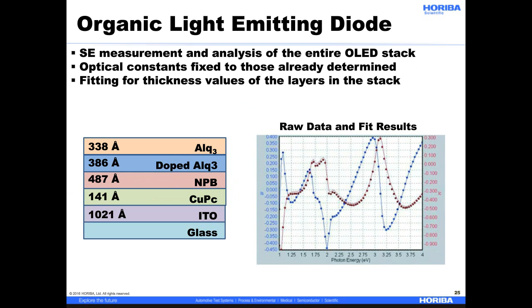Finally, you have the whole stack. This is the SE measurement and analysis of the entire OLED stack. The optical constants are all fixed to those that were already determined, and we're basically fitting for the thickness values of the layers in the stack. You'll see on the right some raw ellipsometry data and the fit results, and on the left you'll see the thicknesses for each layer in the sample.